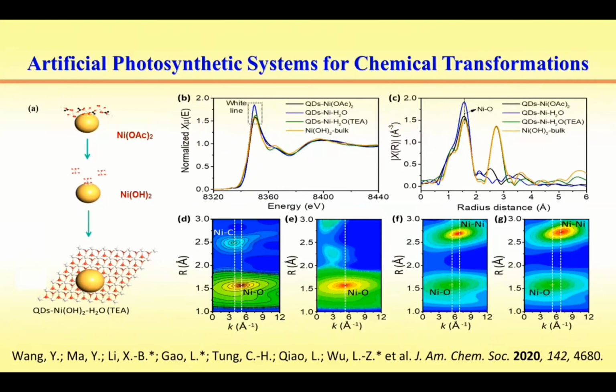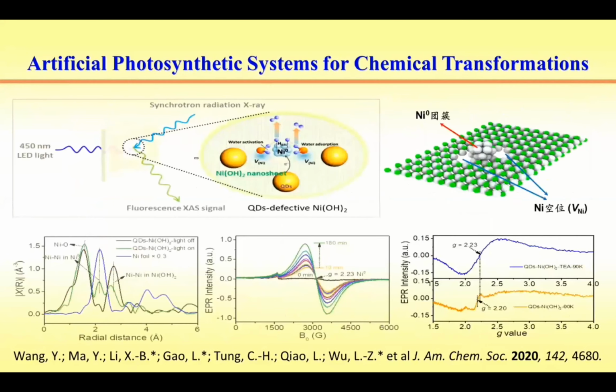these details. In this way, we successfully tracked the structural variation of the catalyst site during typical hydrogen generation. The nickel precursor changes to nickel hydroxide nanosheets in an alkaline medium. Further, operando spectroscopic techniques, such as EPR, show that the photo-induced transformation gives a new catalyst structure, that is, nickel vacancies and nickel clusters.